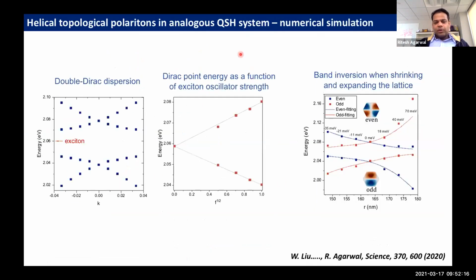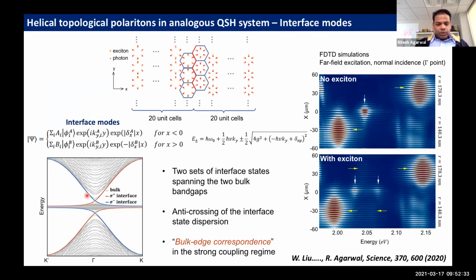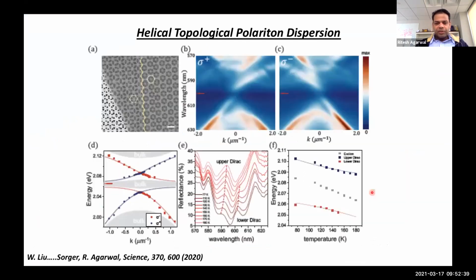This calculation also shows, and we've done experiments to show, that the light matter coupling strength, the square root of the oscillator strength, and the splitting between the two Dirac cones can be tuned. The stronger the coupling strength, the more splitting of the two Dirac cones. And these are the two polaritonic interface states. FDTD simulations also reproduce these results, so everything checks out.